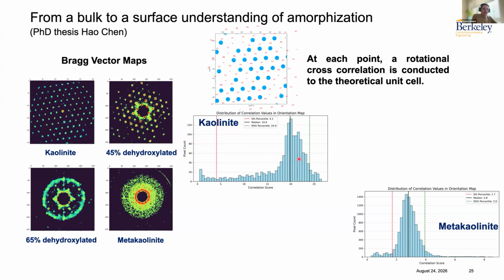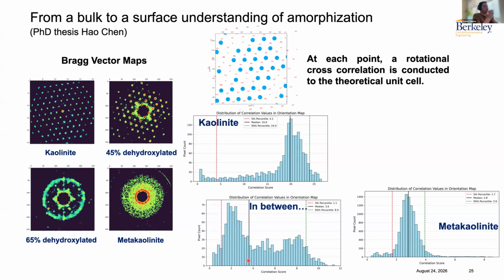What is very interesting, and I won't say much about this, but I just want to motivate critical thinking about it, is what happens in between. While we're moving from kaolinite into metakaolin, you would imagine that this peak moves all at once from this value of 20 until it reaches the 2 to 3 value that we see for metakaolin, that it moves towards the left in this case. However, what we see in between is that rather than having a single population, we start seeing this kind of bimodal distribution, indicating that the degrees of amorphization may not be as uniform within the space as we thought in the beginning.